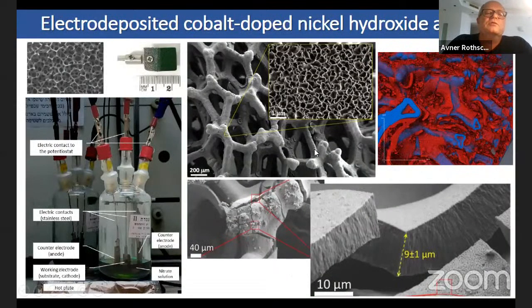So the way we do this is by electrodeposition on nickel foil, so a highly porous substrate, nickel foil. I'm sorry, not nickel foil, nickel foam substrate. And here you have the large pores come from the nickel foam. These are nearly 200 micron voids. But what's important here is the active layer. The active layer is about 10 micron thick of the electrodeposited nickel hydroxide. We also dope it with cobalt to improve the performance.